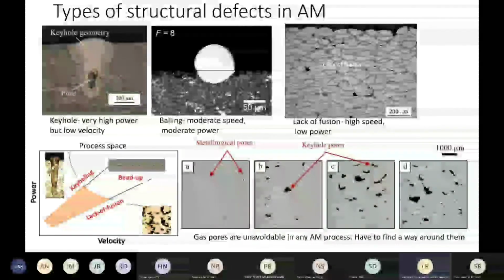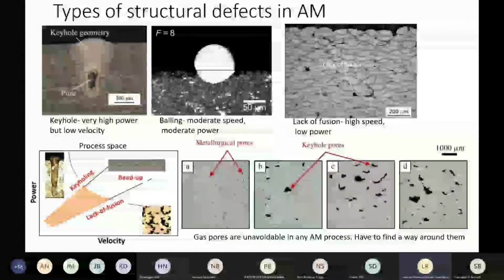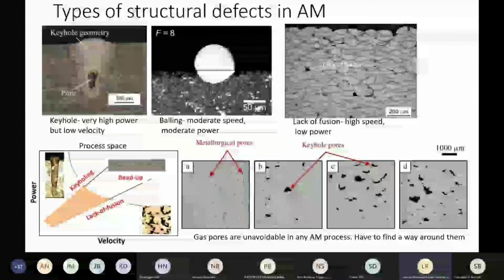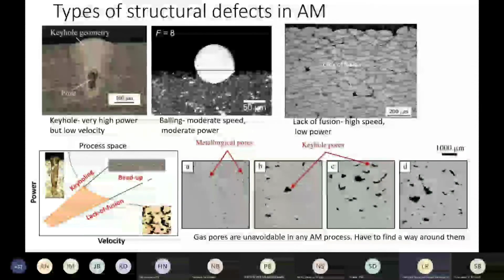Okay. Apart from these, defects form due to gases in the material, which are released when the laser beam runs over the material. So there are going to be gases that are created, which go and sit inside the material as metallurgical pores, known as gas porosities. You can also, of course, have keyhole porosities for some other reason, but we will look at what essentially leads to that. We will have to live with gas pores anyway because it is inherent to an AM process. It is like a welding or a sintering process, and these are powders which have spherical shapes, so they will always result in some kind of gas porosity. But other pores need to be avoided, such as lack of fusion, balling up, and keyhole geometry.